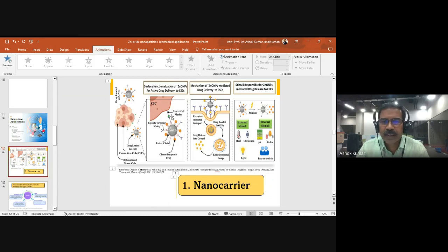Once it gets attached, it enters through the endocytosis mechanism. If you look at the second picture, the prepared zinc oxide nanoparticle enters into the cell. Then zinc oxide is released from the prepared nanoparticle. So it's a dissociation of zinc from the nanoparticles. And we can also incorporate a drug inside the zinc. Once the drug is released at the site, it may produce an action. So we can say it can kill the cancer cells.